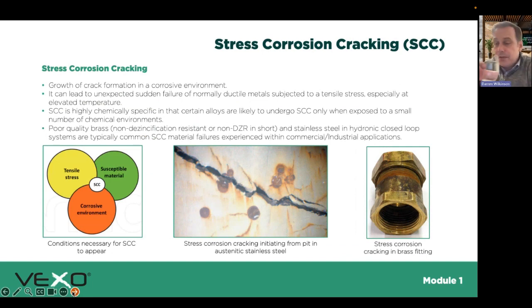And then there's stress corrosion cracking. Doesn't come up as often as the other issues of corrosion, but typically in our industry, you'd see it mostly on chill water systems. Rather like the fire triangle, to have a fire, you need a fuel source, you need heat, and you need oxygen. If you take one of those away, you won't have a fire. Stress corrosion cracking is rather similar. You need a tensile stress. So we've got a hydraulic closed loop system under pressure. We've got connections that have been threaded, under pressure where those joints have been made.